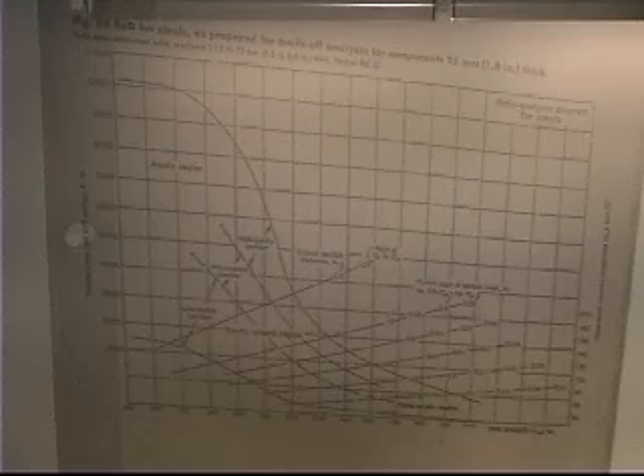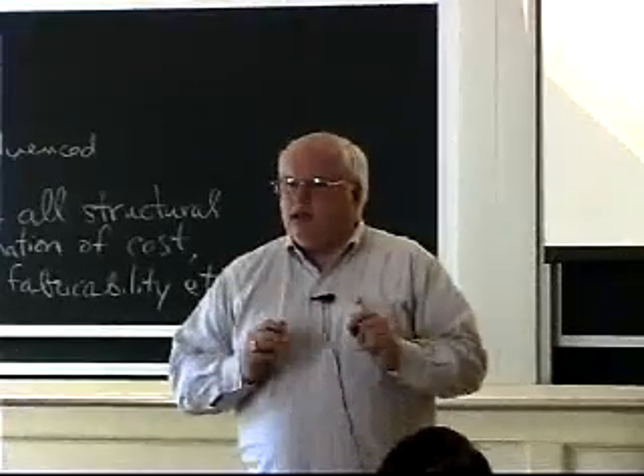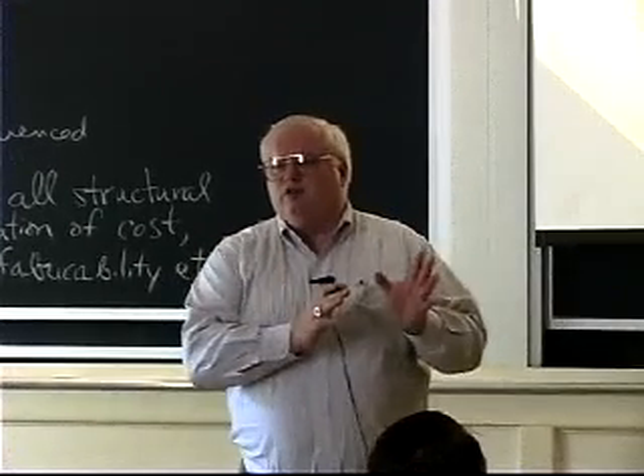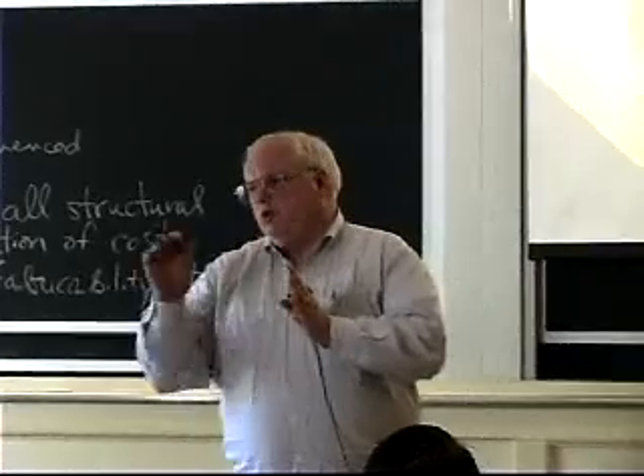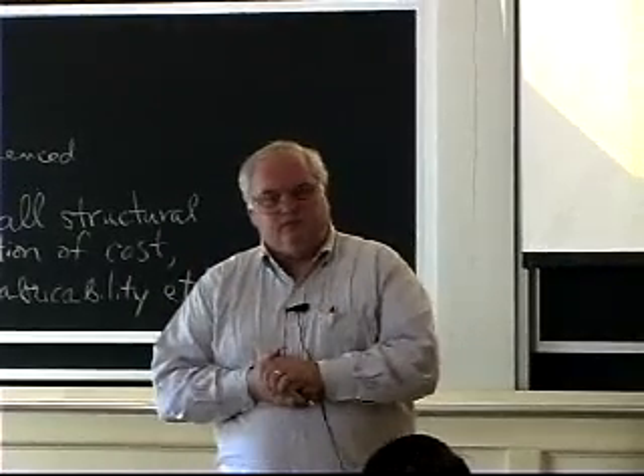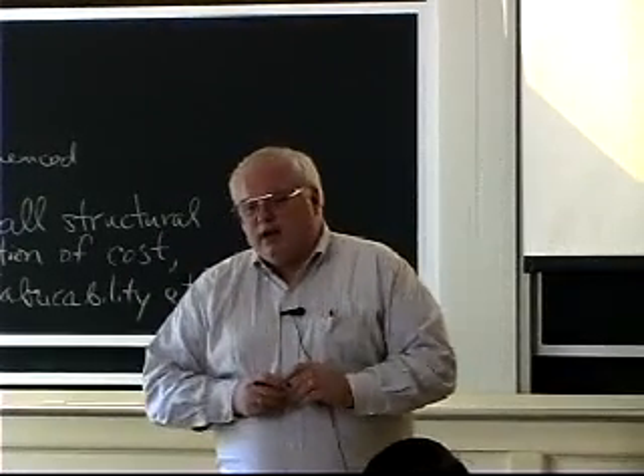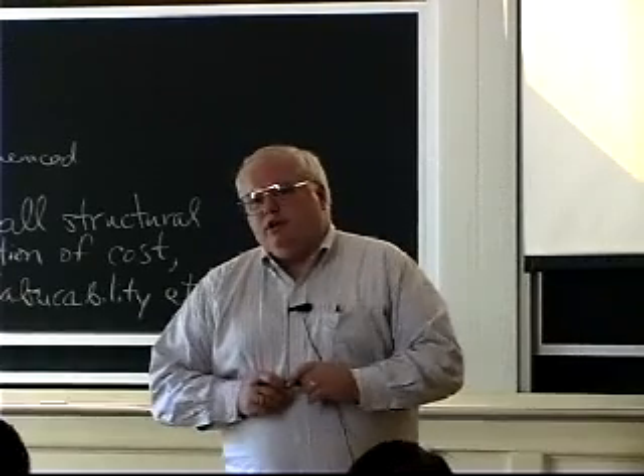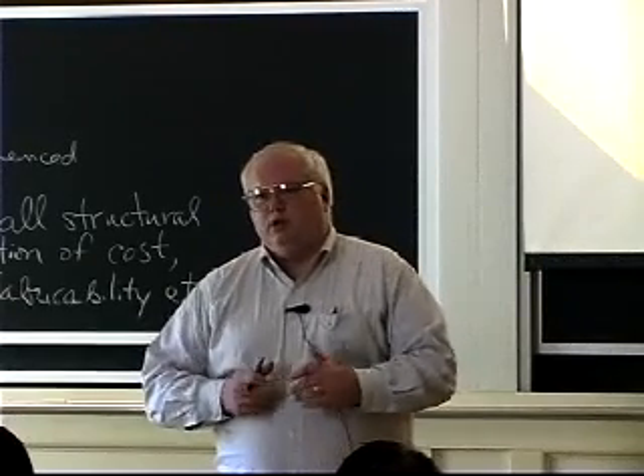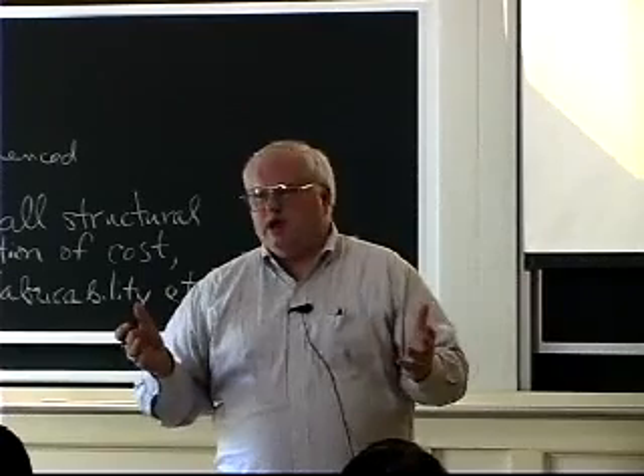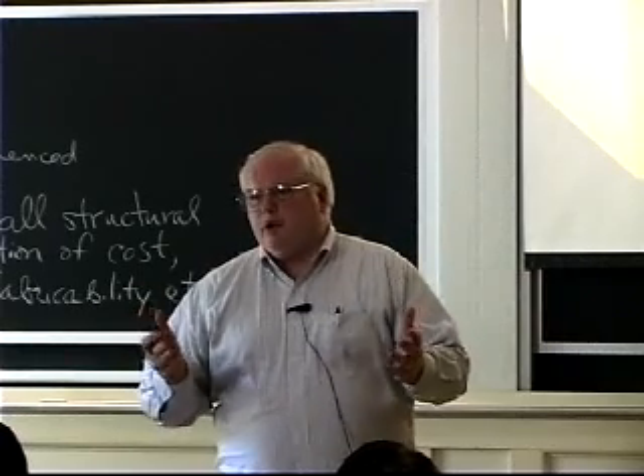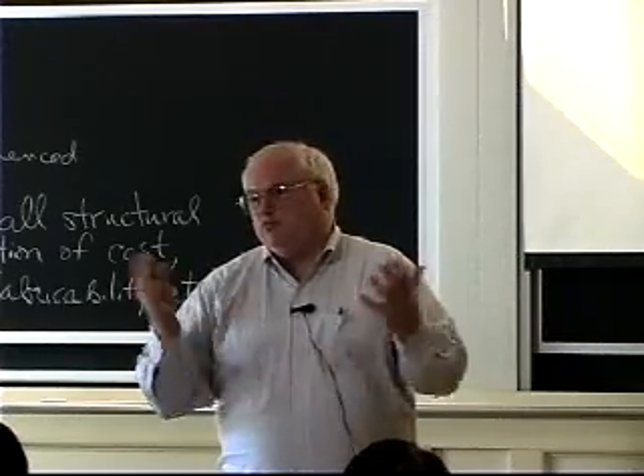Griffith was a scientist in England in 1925, and he came up with the fundamental equation of fracture mechanics, which we'll go through next week. But in any case, he basically said that the toughness of a material is related to the strength times the square root of the crack length, the flaw size. Okay, that's the fundamental equation. That was in 1925. What happened 15 years later, 20 years later, is they built about 5,000 Liberty ships and T2 tankers, and about 200 of them had major cracks, and a few of them sank, just broke completely in two.